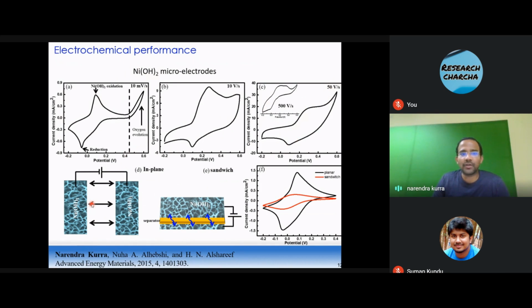This is truly due to the geometry, the in-plane geometry of nickel hydroxide electrodes, where if you compare sandwich versus planar configuration, there are much more enhanced current values in the case of planar configuration, because the diffusion pathways for the ions are short in the planar configuration compared to the sandwich, where the separator is the limitation.